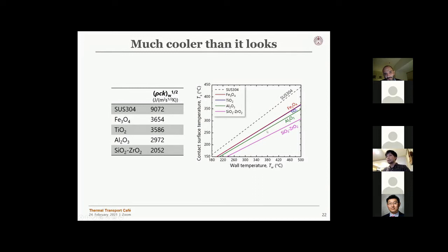And on the right-hand side, I plotted the contact surface temperature calculated by this model as a function of wall temperature, to see how much gap we have between the two.